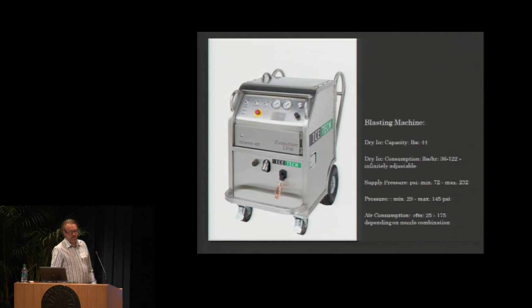This is our blasting machine. It has a holding capacity of 44 pounds. It can shoot out 36 to 122 pounds in an hour. So it can really throw out some ice. Supply pressure, 72 to 232 PSI. And we have a minimum of 29 to 145. And then the air consumption rates are 25 to 175.